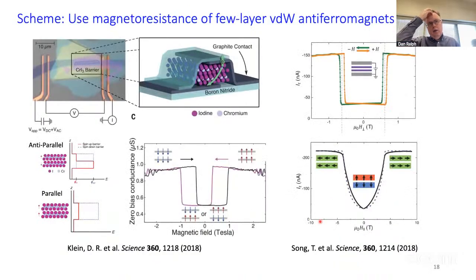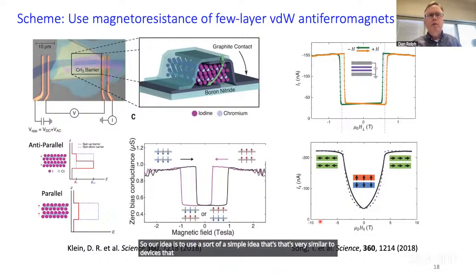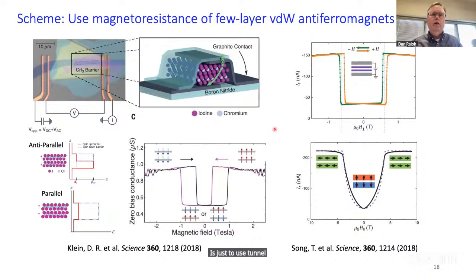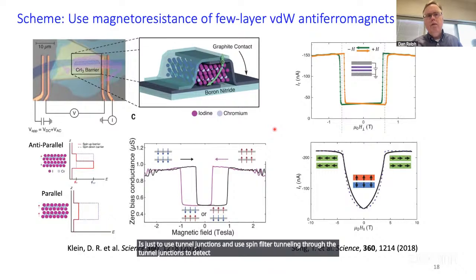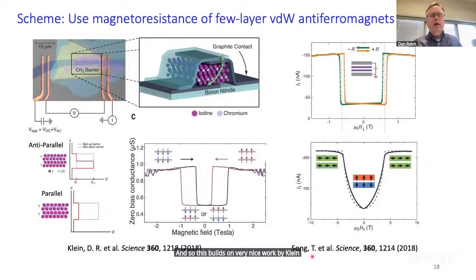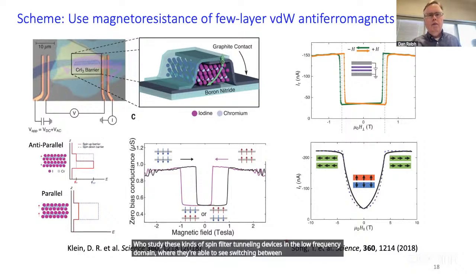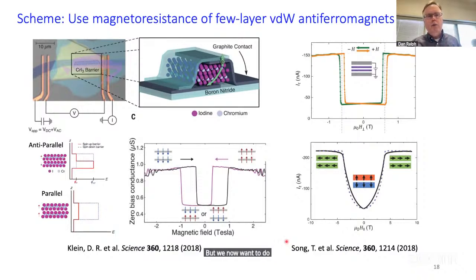So our idea is to use a simple idea that's very similar to devices that have been made previously with some of the chrome triiodide related antiferromagnets, which is just to use tunnel junctions and spin filter tunneling through the tunnel junctions to detect not just the relative orientations of the spin sublayers in the antiferromagnet, but also their dynamics. This builds on very nice work by Klein et al. and also Song et al., who studied these kinds of spin filter tunneling devices in the low frequency domain, where they're able to see switching between parallel and antiparallel alignment. But we now want to do this in the high frequency domain, looking at the dynamics.